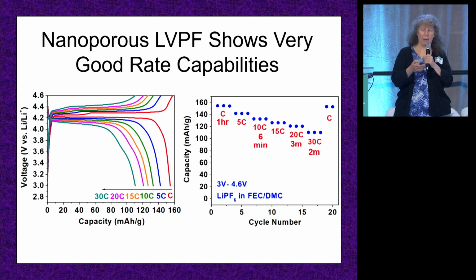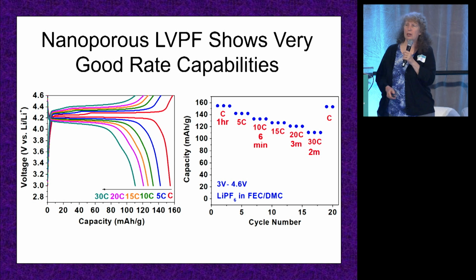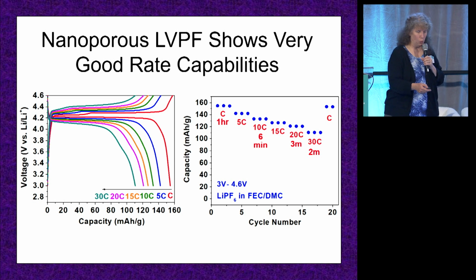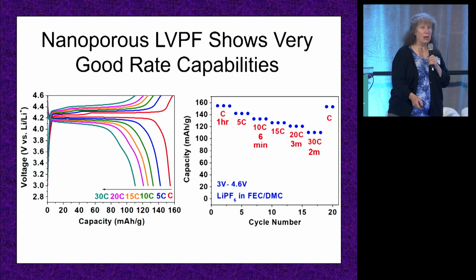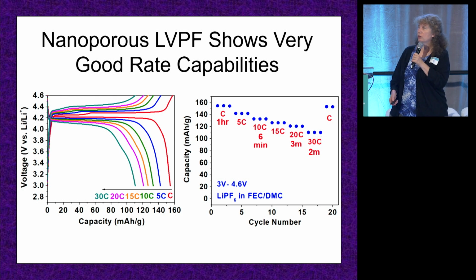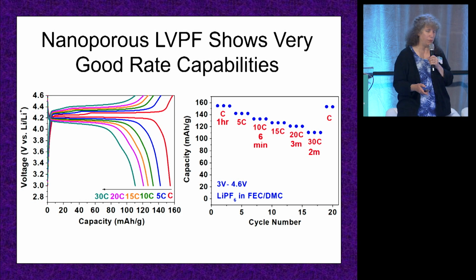So for those of you who are battery aficionados, this is the raw data. Most of you just want to look at graphs like this one. So on the y-axis, we have capacity. And what we do is we cycle our material faster and faster and see how much of the capacity it retains. So we use this notation 1C. 1C means we charge in 1 hour. 10C would be 1/10 of an hour or 6 minutes. 30C would be 1/30th of an hour or 2 minutes. And you can see that this material does not lose much capacity as you charge it faster and faster.